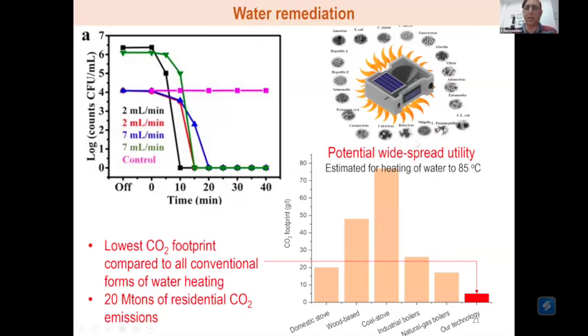Most of the pathogens are unstable at this temperature. So we ended up doing some experiments where we take some known concentration of pathogens and try to see what happens when the water comes out. We see that all the pathogens, even if we start at about 10^6 CFU per ml concentration, we end up getting almost nothing in the output water.